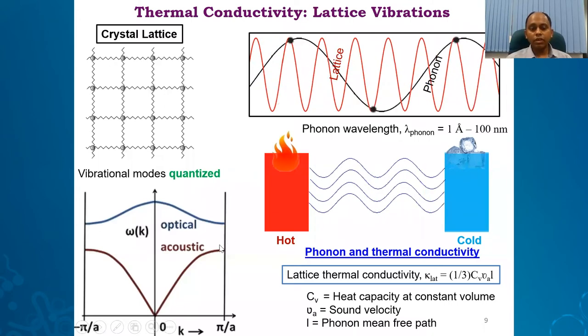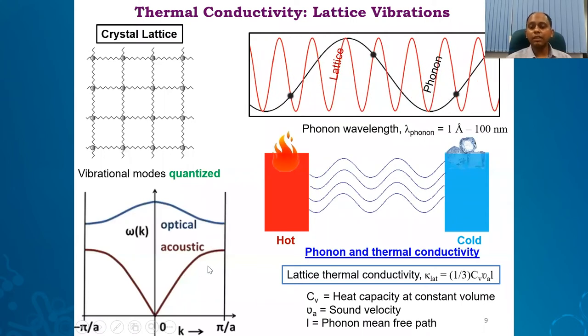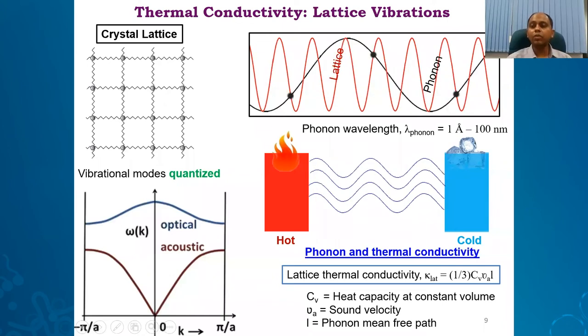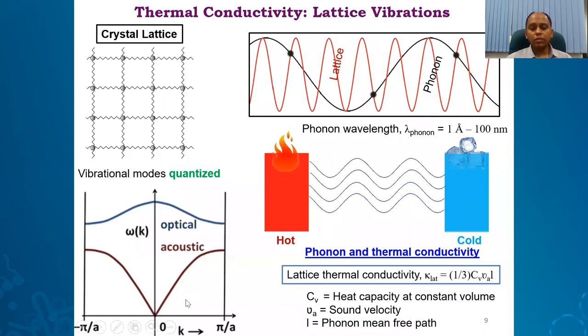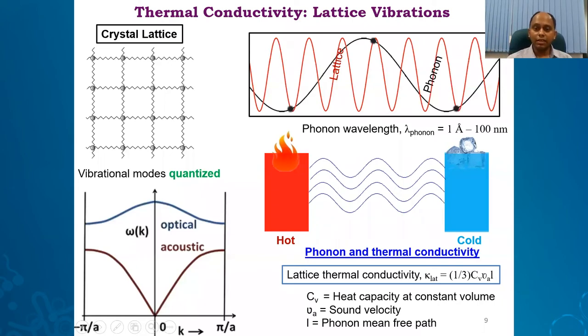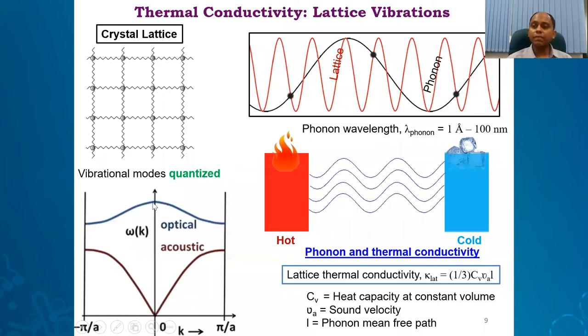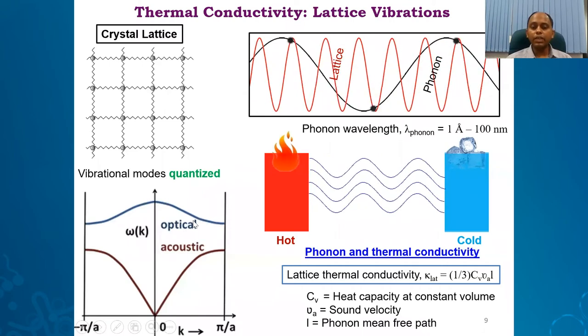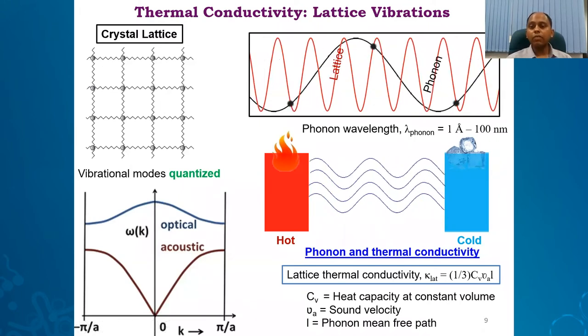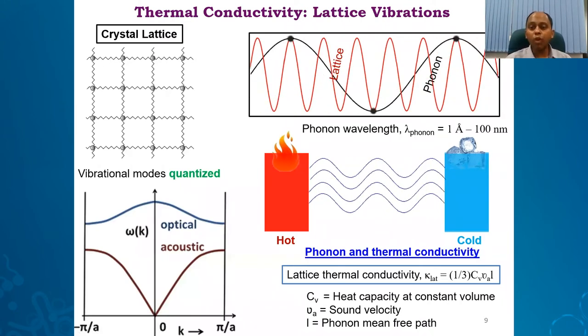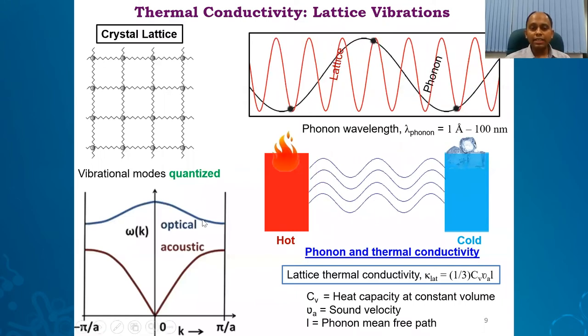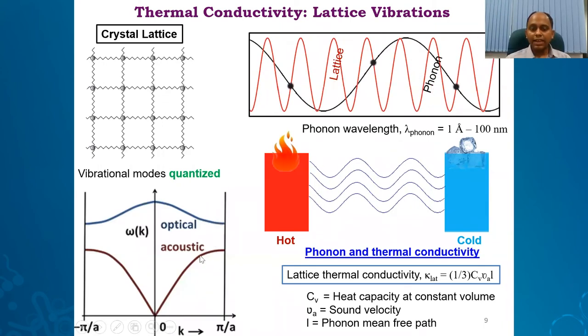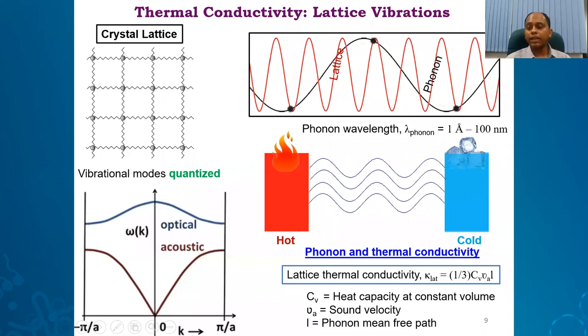There are two kinds of phonons. One is the acoustic phonon — essentially sound waves traveling through a solid — generated when all atoms vibrate in the same direction. When different atoms vibrate in different directions, these are called optical phonons, which develop a dipole moment measurable by Raman or terahertz or IR spectroscopy. There is always an energy gap between optical and acoustic phonons. Please note: only acoustic phonons carry heat in a solid material and are responsible for thermal conductivity.